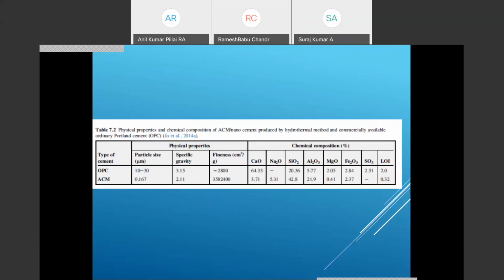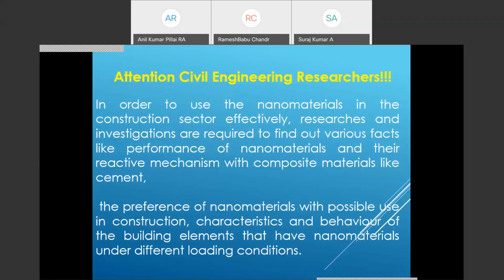And the calcium oxide content is reduced, and sodium oxide is present at a composition of 5.31 percent, and silica is present at 42.8 percent. Aluminum oxide increases to 21.9 percent. Magnesium oxide gets reduced. Ferric oxide gets reduced, and this type of chemical composition could be possible in the alternate material or ultra fine cement. So it draws the attention of civil engineering researchers to use nanomaterials in the construction sector effectively.